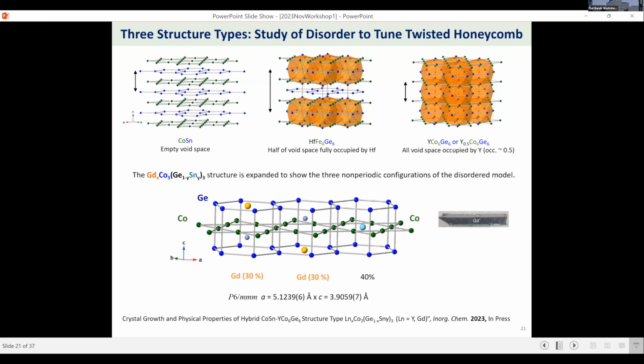There are also alternate media to grow intermetallics. We have been able to grow intermetallics at 600-700 degrees, which is not 1100. Most of these materials actually turn out to be about 900 with the main metal flux. But we do think about that.